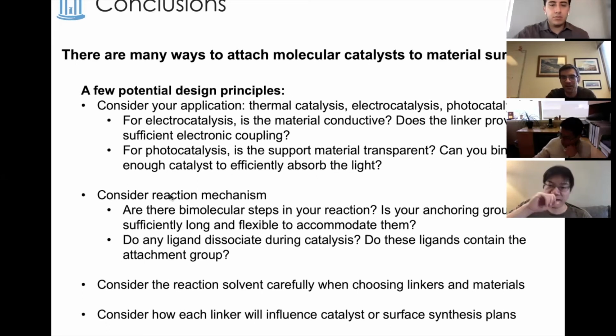Considering reaction mechanism is important. And I would argue, I'll give just two examples of where that can play an important role. One is if you have a bimolecular reaction. So for example, in some water oxidation catalysts, two ruthenium oxos from two different catalysts need to come together to form an oxygen-oxygen bond. But if you anchor your catalyst to the surface, that may not be possible to geometrically get to the right configuration to form the OO bond. So you may need a long flexible linker to enable the two catalysts to find each other.